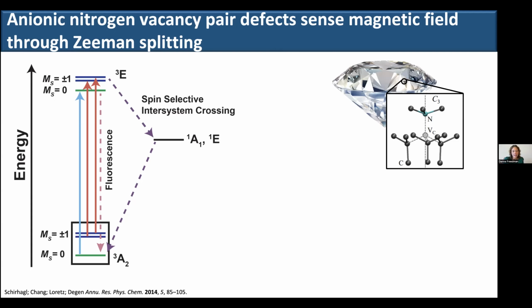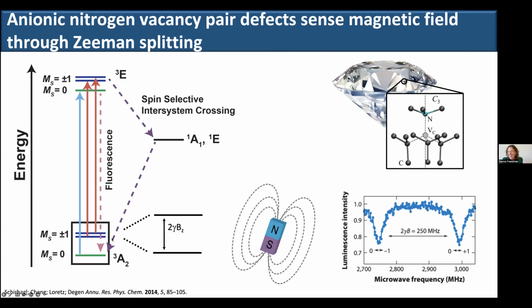This defect creates this electronic structure shown here, which you can use to optically pump and polarize a small 0.1 wave number energy difference with an optical wavelength, which is like 15,000 wave numbers. And then using fluorescence, you can read out the spin population. And so effectively, this is a magnetometer. Another way to phrase this is that you can read out the splitting between the M sub S levels, which means that you can read out your magnetic field.